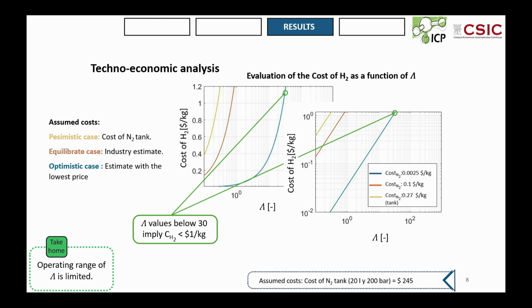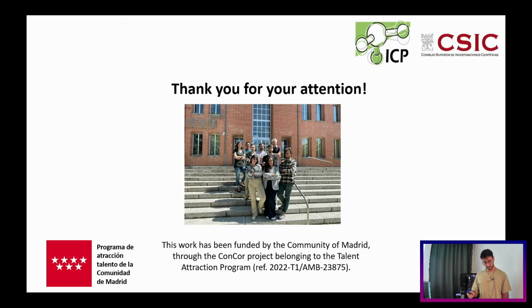We could also make a techno-economic analysis, and we saw that the cost of production of hydrogen is highly dependent on the lambda values. And we fixed a threshold where lambda values below 30 would imply a cost of hydrogen below $1 per kilo. And that work allowed us to make some conclusions, like the main parameters that affected the process, that it is not that desirable to achieve the chemical equilibrium, how the countercurrent outperformed the fixed bed, and that values of lambda greater than 30 will increase the cost of hydrogen production above $1 per kilo. And that's all, and thank you for your attention.